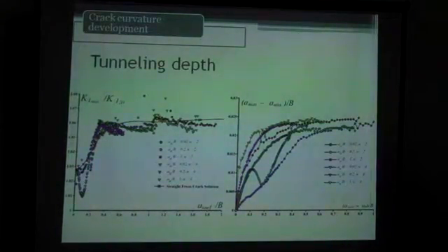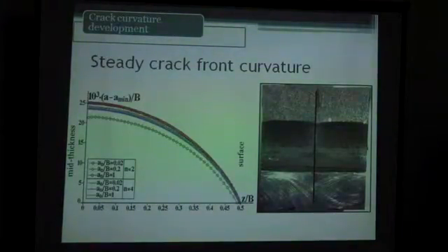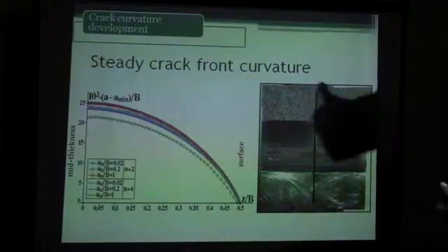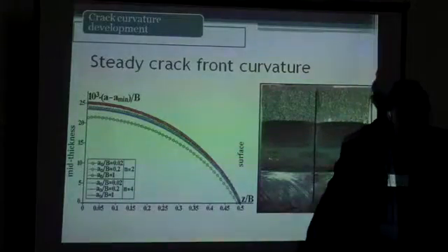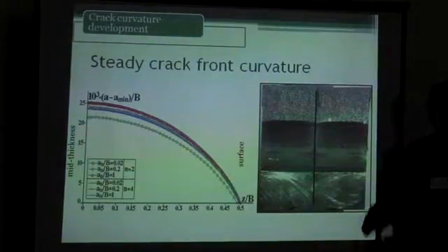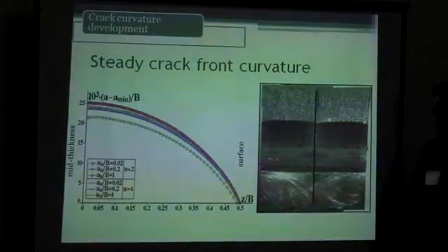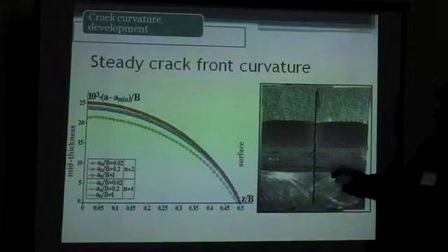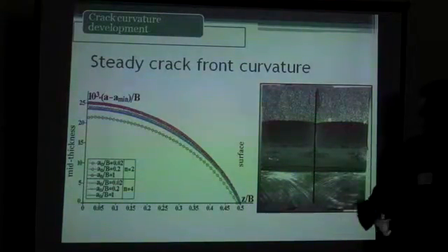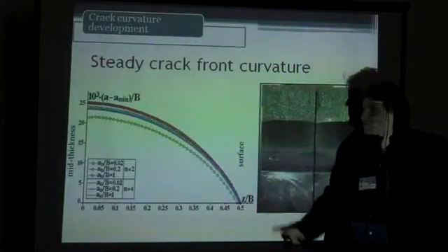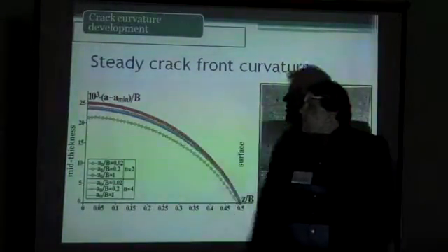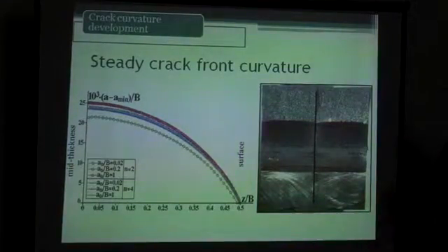So this is very significant because now, if you consider a straight crack, you're going to have some value of K1 that varies along the crack front. However, when you allow it to turn, you're going to see that it tries to follow an iso-K1 value, so all these points along the crack front will try to follow it.